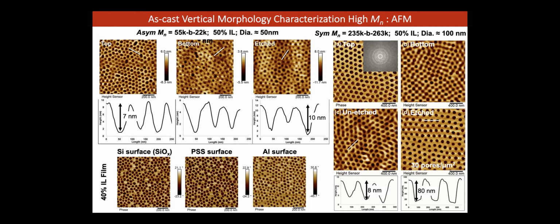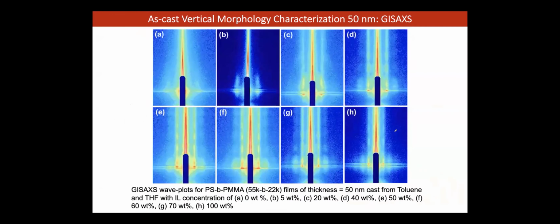You wouldn't think that ionic liquid would evaporate, but actually they do. And even in half an hour of annealing, they can get rid of them. Okay, so now this is where GISAXS comes in. Do we really think that the AFM structure percolates all the way to the substrate?